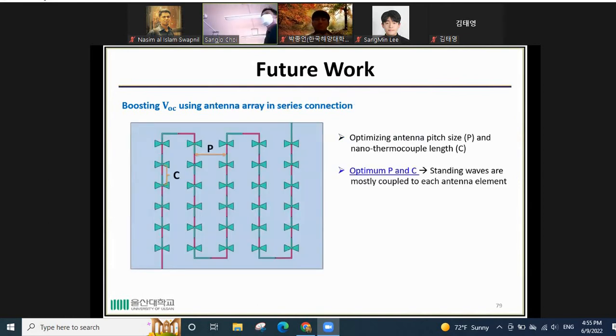And the second way to increase the output voltage is by arranging the antennas in an array, in series connection, by optimizing the pitch size and also the nano thermocouple line. Because as I mentioned before, this pitch size depends on the standing wave. That's why we need to optimize the pitch size and also the nano thermocouple line to find the optimum pitch, so that the standing wave is mostly coupled to the antenna element, and higher VOC is then achieved because of this array structure.